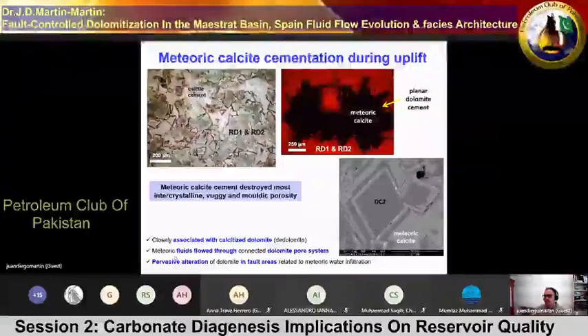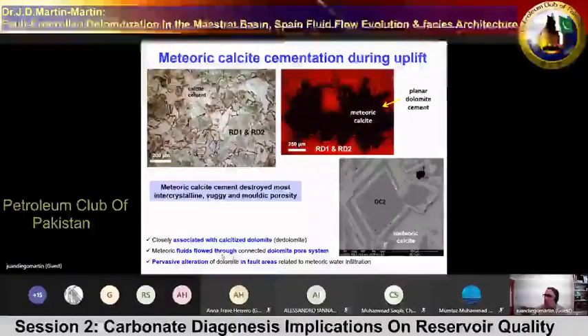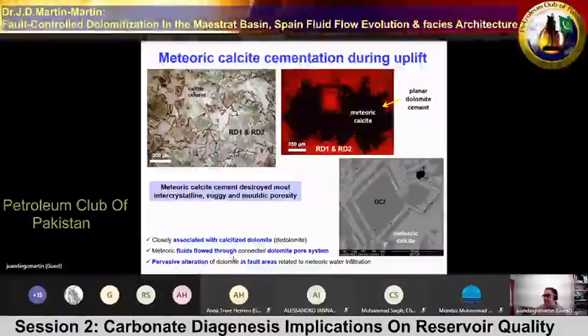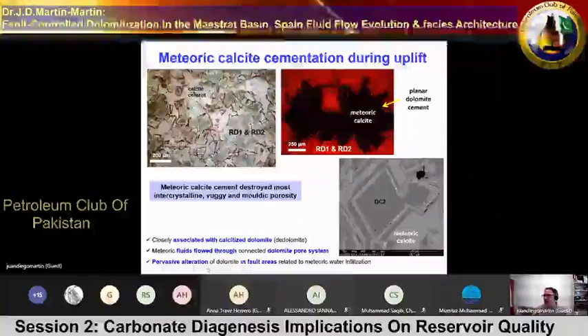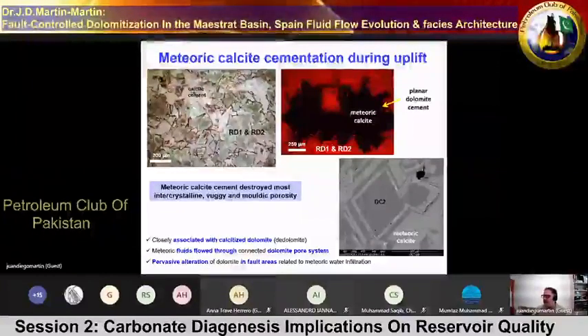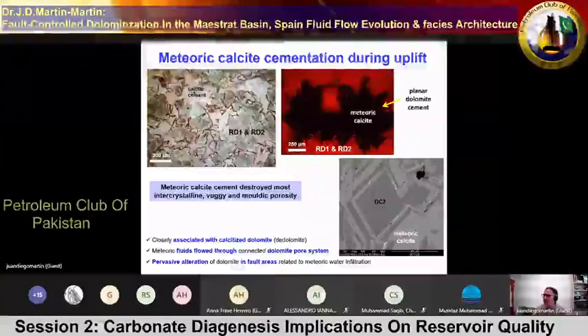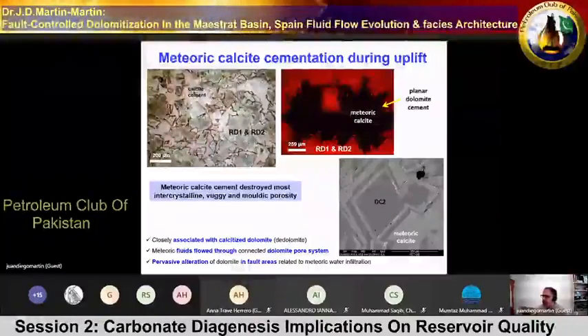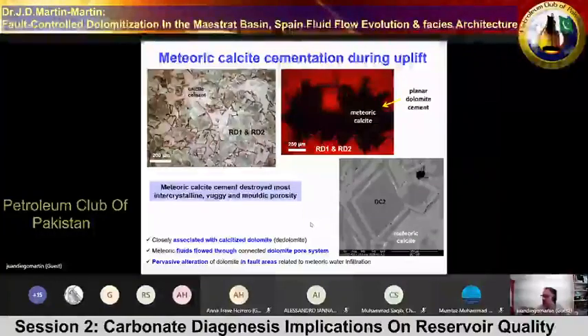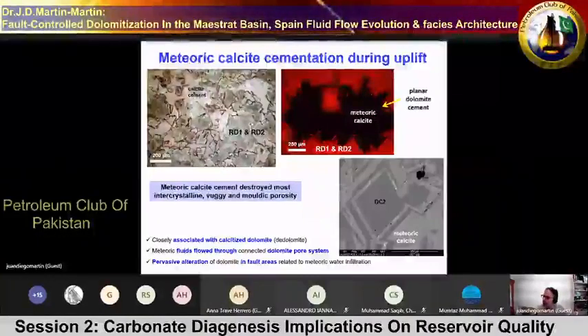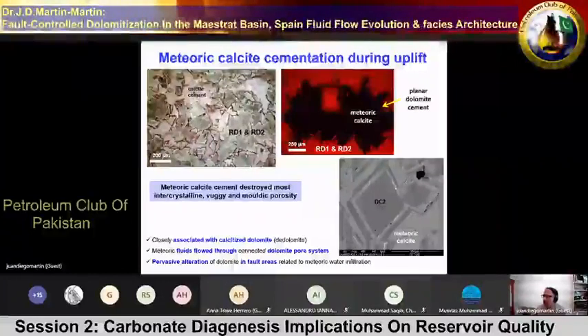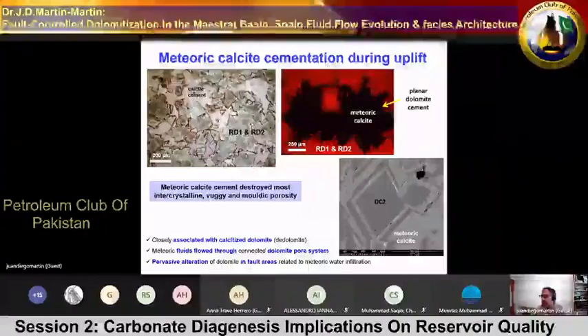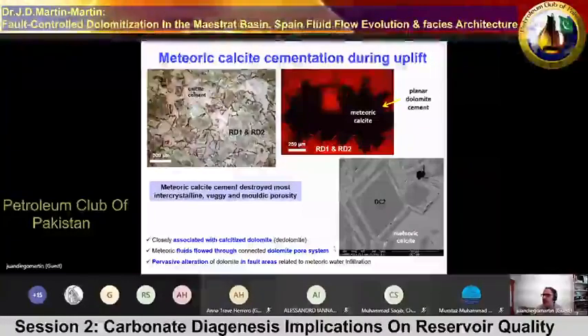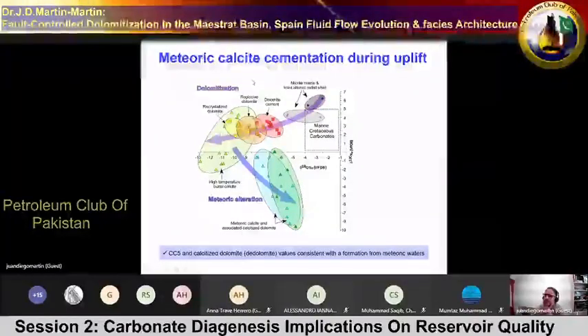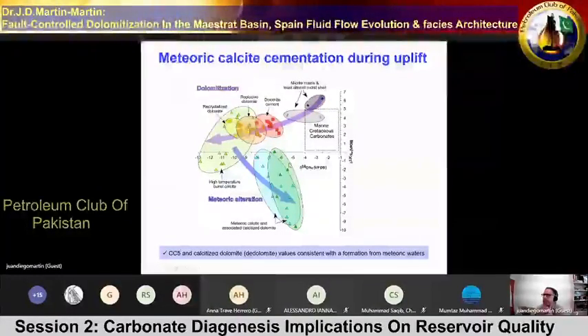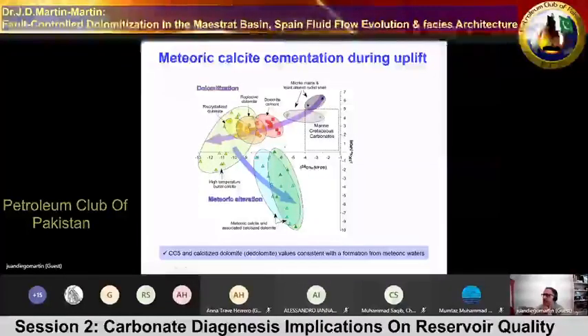It occurs via meteoric fluids that flow through the connected pore system, and there is a pervasive alteration of dolomite in fault areas where the meteoric water infiltration was more active, and in this area the dolomite is completely de-dolomitized or calcitized. We have a lot of iron oxide around, and a very dark orange, brown, red color dolomite, indicating that the dolomite itself is partially de-dolomitized or calcitized.